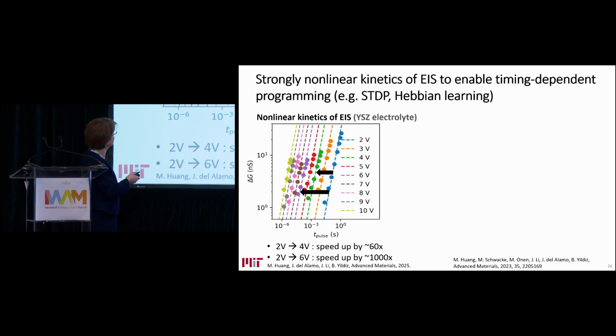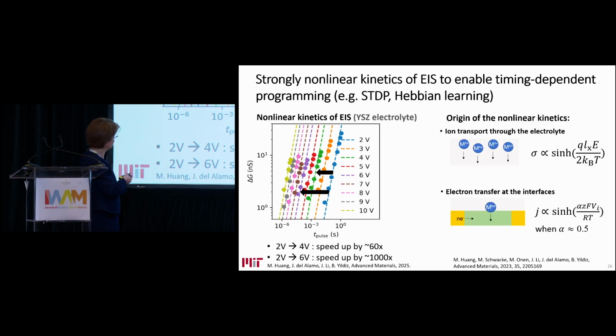So if we look at the order of magnitude of this nonlinearity, we can see here that, for example, if we double the programming voltage from 2 to 4 volts, we get a speed up of about 60-fold. If you triple it, it's a 1,000-fold acceleration of the response. So it's strongly nonlinear, and as I said earlier, this comes from the nonlinear dependence of ion transport on the field across the electrolyte and the nonlinear dependence of electron transfer reactions on the field at the interface.